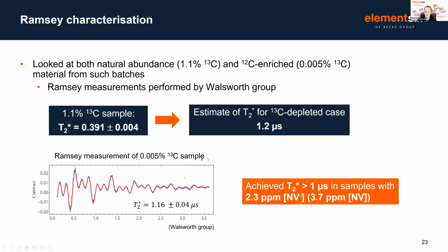So what we've demonstrated is that we can achieve coherence times that are then competitive with that 1 ppm recipe that we introduced earlier, by depleting the levels of carbon-13 in what is otherwise a high concentration of NV centers. So in that sensitivity equation, we have this idea of the product of the NV concentration and T2 star affecting the sensitivity. And clearly in this sort of material, we have a very favorable product. So we would expect this to translate into a high sensitivity in practice.